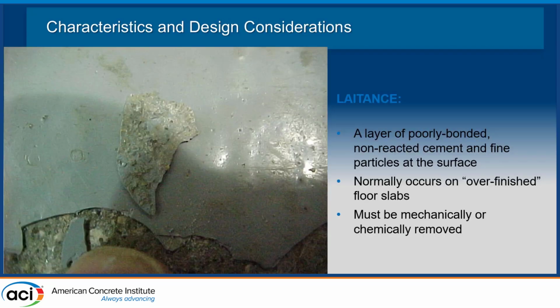So, laitance. This is an example of where a coating was applied over laitance that were not removed. And as you can see, the coating adhered perfectly. It's just the laitance came loose. So as much as that looks like a coating failure, that's actually a surface prep failure, because the laitance were not removed. The coating sticks to the laitance, which have a very low tensile strength, and it comes loose from the surface, and then we have a problem there.